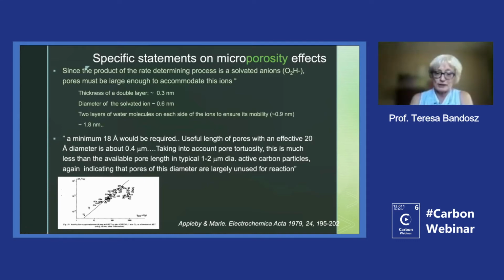for oxygen reduction. The authors studied many carbons, and of course those carbons were not modified with nitrogen. So they were the porous ones and non-porous ones. And based on the dependence of the current on the surface area, they stated that the pores in the carbons of high surface area are not really important. And they, in fact, had a reason to state it, because of the geometrical constraints.